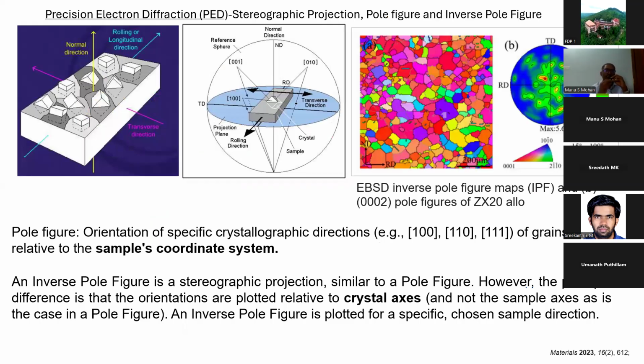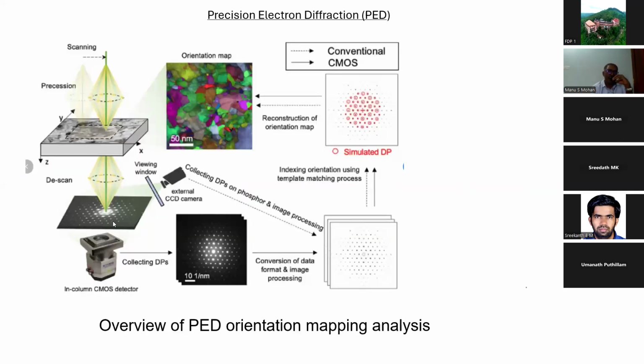Here, instead of Kikuchi patterns, the diffraction pattern from each point is captured using a camera. You can see a camera here. The camera acquires each of these diffracted beams as the beam rasters the specimen. As the beam scans each point in the specimen, you record the diffraction pattern using a camera, and each point is compared with the theoretical pattern. Suppose you are doing iron, you already tell the system the material is iron, so these are my lattice parameters, these are the atomic coordinates, all those things you load free of cost from various websites. Then the system will simulate those patterns and compare them with the experimentally acquired diffraction patterns. That is what is done here. Then they will give a color code, orientation mapping, all those things.